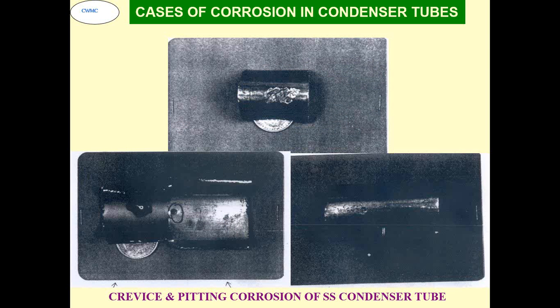These are the stainless steel condenser tubes which were transported through sea route, and either during transportation or during storage, seawater has ingressed into the system, and from the portion where the ropes were tied, below that portion crevice corrosion took place and the tubes lost their thickness. When they were hydro tested, almost 700 tubes failed during the hydro test. Of course, tubes were replaced by the vendor, but commissioning time of about 1 year was lost.